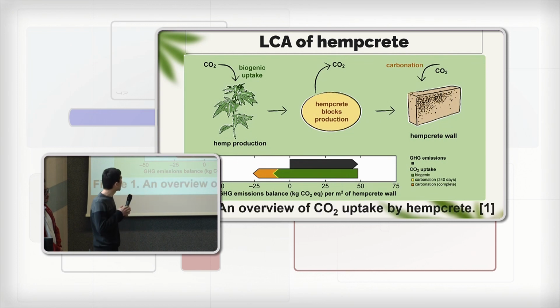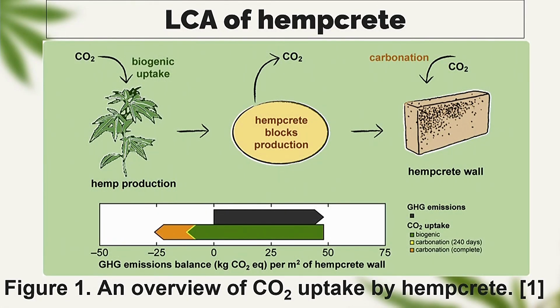In this figure, you can see an overview of CO2 uptake by hempcrete. This is from a study. Just like any other crop, during its growth, it absorbs CO2 from the atmosphere for the photosynthesis reactions. But during the block production, there is a lot of CO2 emitted as well. After the production, during the life of the block, there is a process called carbonation. In chemical terms, it's a reaction of carbon dioxide with calcium hydroxide or calcium silicate hydrate to produce calcium carbonate and water. So basically, it absorbs more CO2.